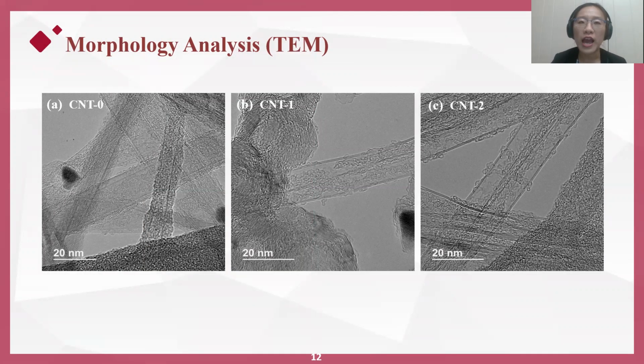The internal structures of the as-collected CNTs were reviewed with high-resolution TEM in this slide. For the control CNT group, the predominant component observed was multi-wall, with diameters ranging from 19 to about 23 nanometers. The addition of deionized water into the catalyst solutions transitioned this composition towards more double-wall CNTs. Double-wall CNTs started to emerge in the CNT1 samples, accompanying some multi-wall with more than 10 walls. With an even higher water concentration, the CNT2 group demonstrated a great majority of double-wall CNTs, and the diameter range was from 10 to 15 nanometers.